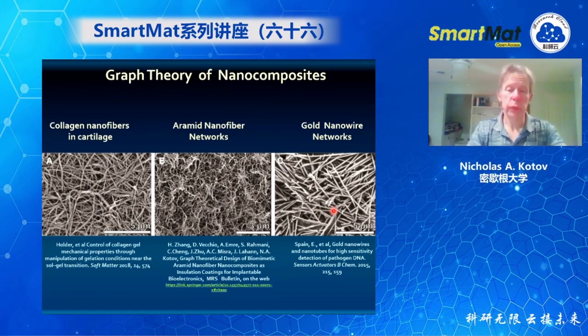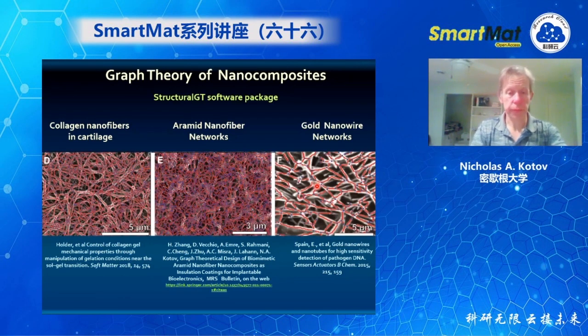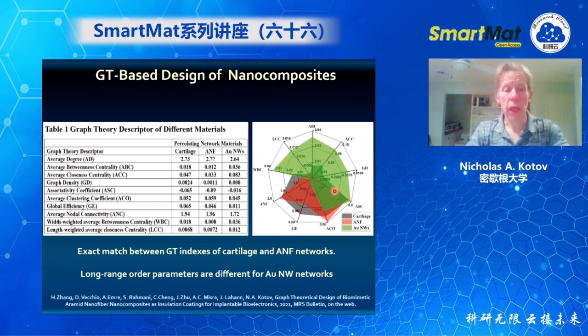And also, for comparison, we looked at the network from gold nanowires. We used a computational tool called structural GT to extract the graph theoretical representation of these composites from SEM images. And after that, we can analyze that graph, compare it to aramid nanofibers and to gold nanowires. Very interesting, I was very happy to see that, not expecting too much. It turns out that cartilage and ANF share structural indexes which almost overlap each other.